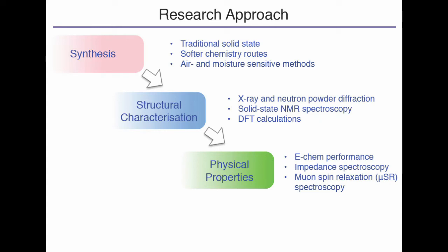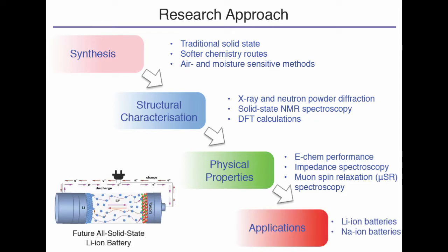Once we've characterized our material, we then start to think about the physical properties. So could these materials perform as electrolytes? So we want to look at things like their electrochemical performance, so how they perform in a cell, look at the impedance spectroscopy to look at how ions hop within a material, and then we use this technique known as muon spin relaxation, which also tells us about hopping of ions within a material. Once we've sort of characterized our potential for physical properties, we can then start to think about applications, putting these things into lithium and sodium ion batteries, and then ultimately, the desirable goal is to finish by putting it into a future all-solid-state battery.